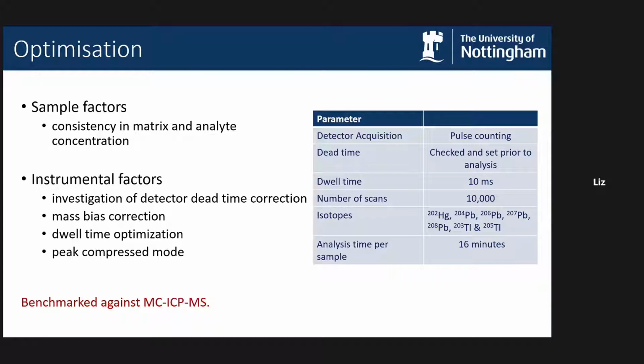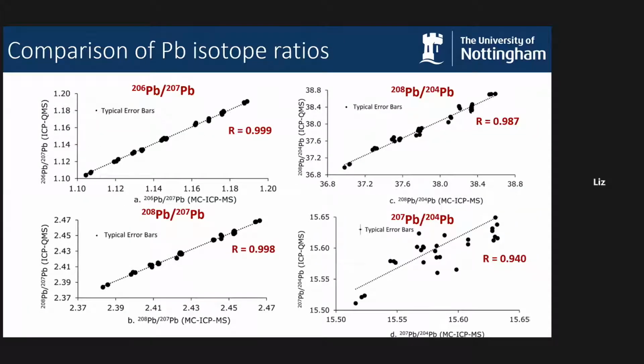So what were the results? How well did we manage to optimize the quadrupole method against the accepted multi-collector method? Well, here I show 4 isotope pairs for you. If you look at the graph on the top left here of the 206-207 ratios, we've got the multi-collector data on the x-axis and the quadrupole data on the y-axis. And you will see that for the 206-207 and the 208-207 ratios on the graph below, we got really excellent correlations and very, very good agreement with the multi-collector instrument.